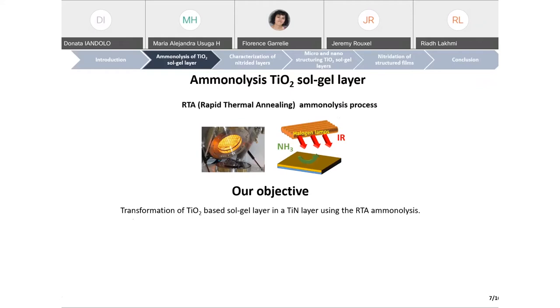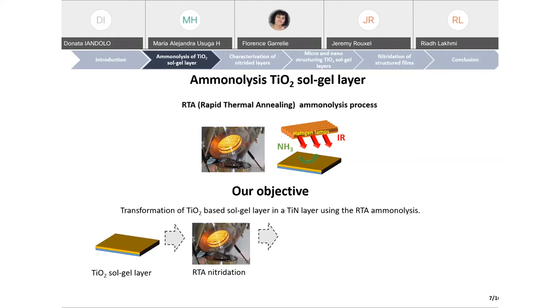At first, we want to test this technique. We want to deposit the sol gel layer using the spin coating method. We do the RTA nitridation process, followed by the characterization of the layer. If we obtain titanium nitride, the process is validated and the realization of micro and nanostructures will be carried out.